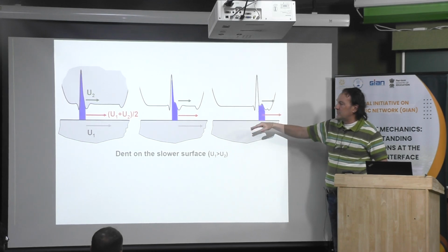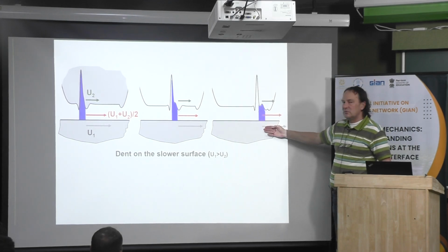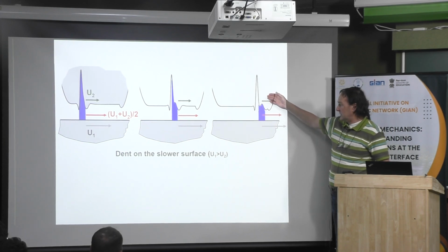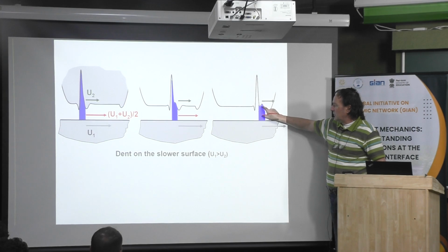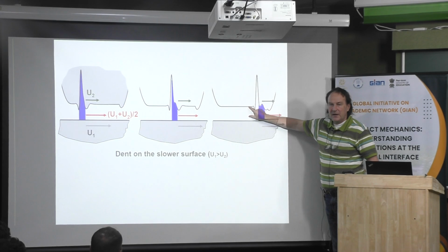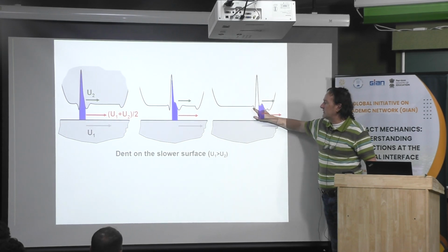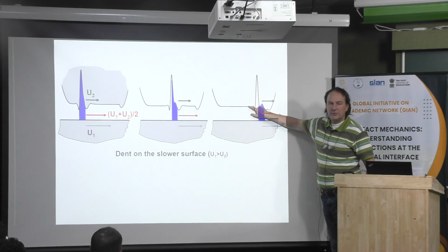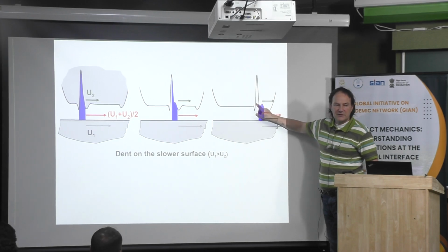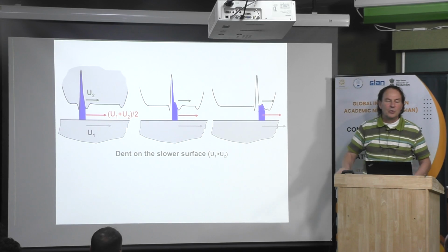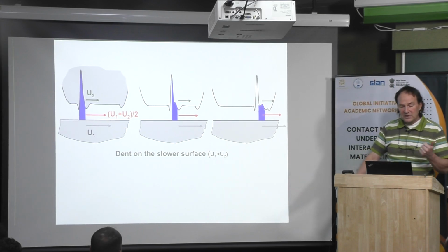This is the opposite if you have the lower surface which is moving slowly compared to the top surface. Then the oil within the pocket will move slowly, and then it will mark and dent the surface behind the dent. Okay? Then this mechanism is very important to make a difference between pure rolling and rolling plus sliding.